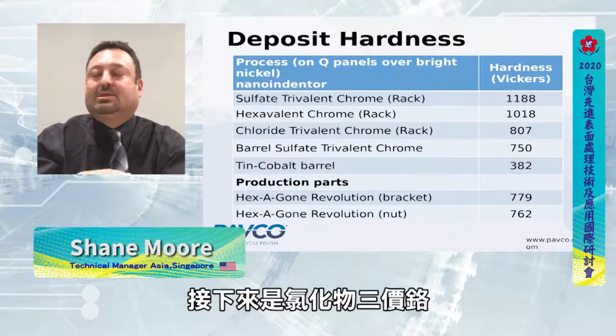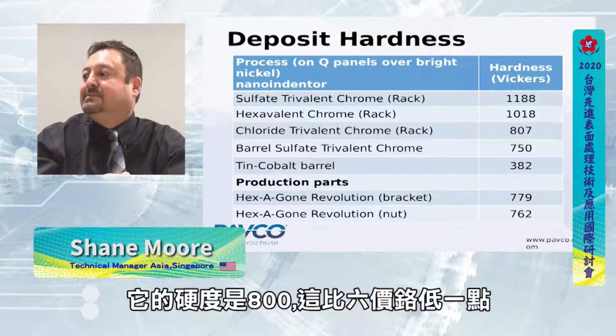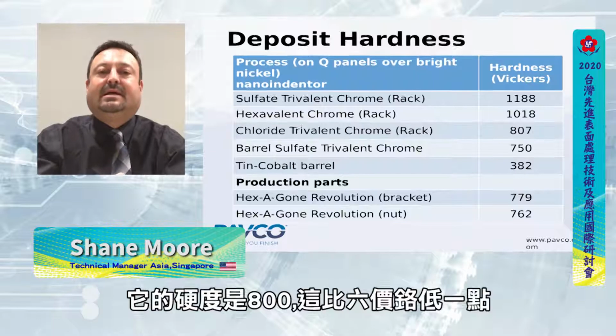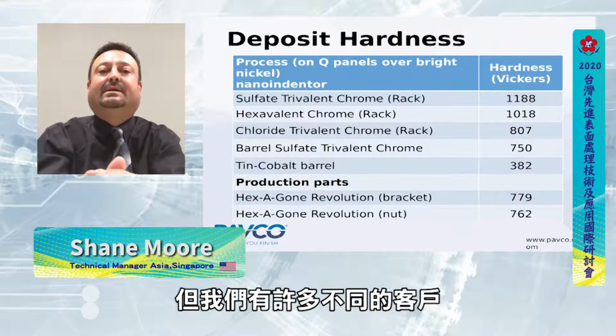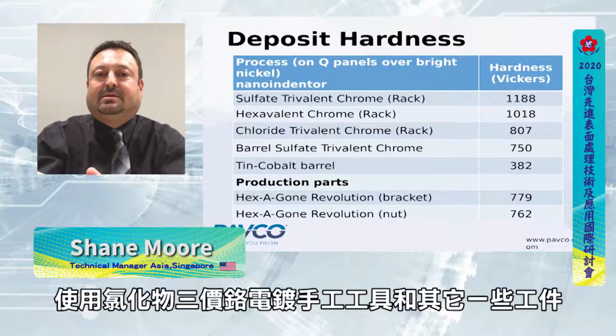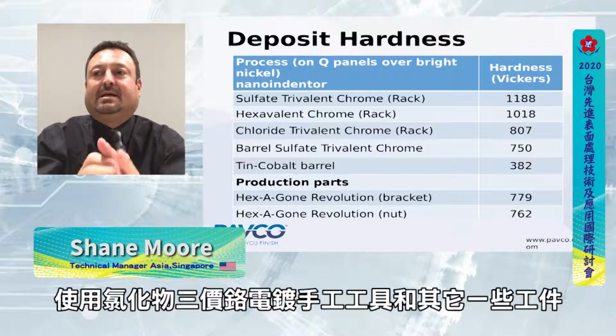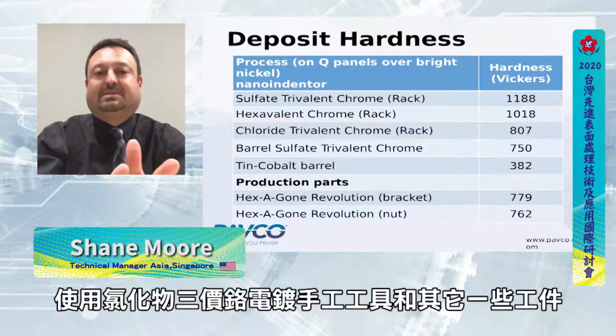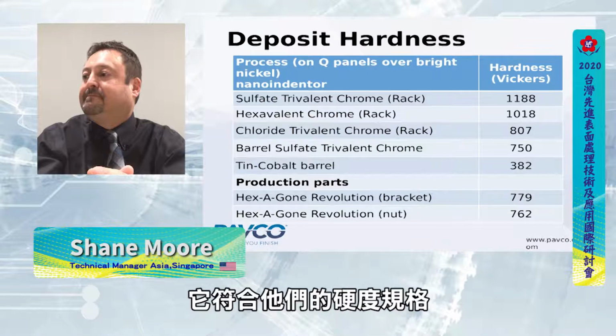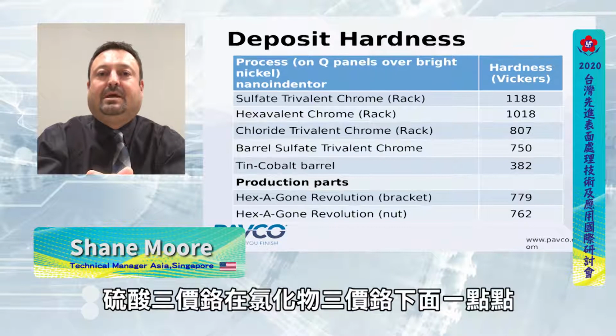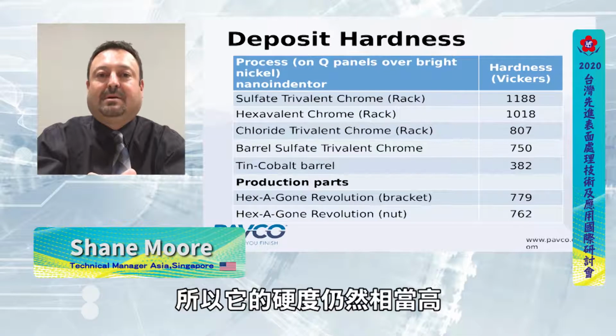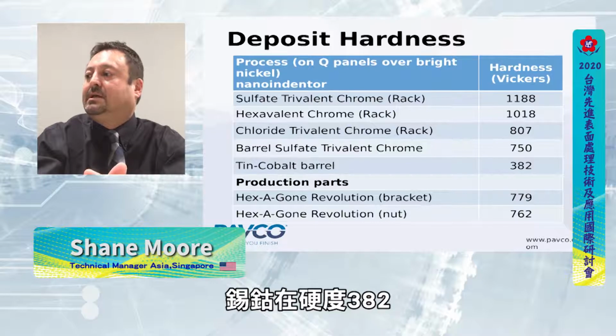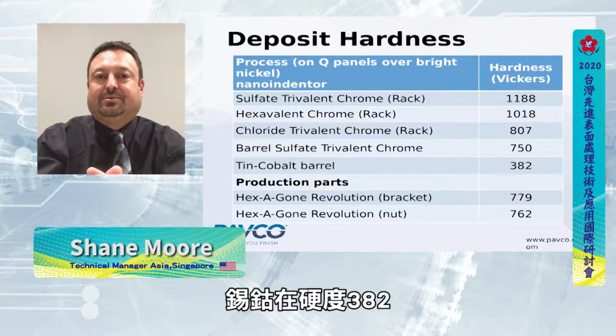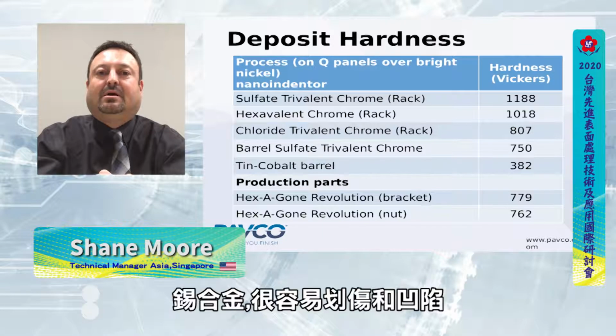So next under that is chloride trivalent chromium. It comes in at 800, which is just a little less than the hexavalent chromium, but we have many different customers that are using the chloride-based trivalent chromium on hand tools and some other things, and it meets their hardness spec, so it's definitely hard enough. The barrel sulfate trivalent chromium came in just under the chloride trivalent chromium, so it's still a pretty hard deposit. And then of course the tin cobalt, it came in very low at 382, and that's just because of the tin-rich alloy.